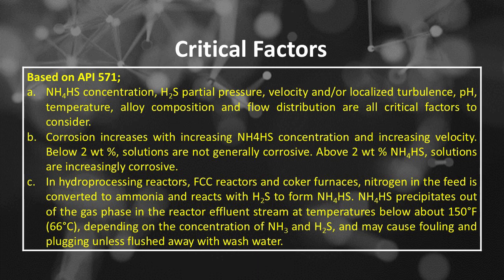Ammonium bisulfide corrosion or alkaline sour water. Critical factors based on API 571: A, NH4HS concentration, H2S partial pressure, velocity and/or localized turbulence, pH, temperature, alloy composition and flow distribution are all critical factors to consider. B, corrosion increases with increasing NH4HS concentration and increasing velocity. Below 2 wt%, solutions are not generally corrosive. Above 2 wt% NH4HS, solutions are increasingly corrosive.